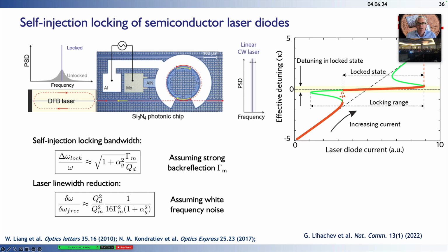That is to say that in a certain current range, the laser frequency that the DFB will lase on is not the innate frequency of the laser itself, but rather is determined by the back reflected light from the external circuitry. What is interesting and unique about self-injection locking is that it allows you to reduce the linewidth of the free running laser. This is done in proportion to the quality factor of the resonator, in fact inverse Q squared. So a very high Q external resonator will significantly reduce the linewidth.